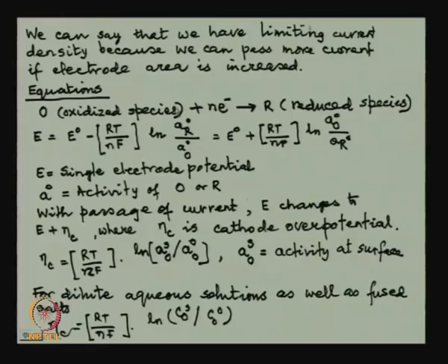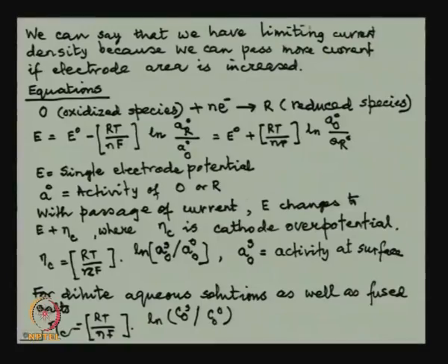Basically, an oxidized species like say metal ion is at the surface acquiring electrons to produce a reduced species. The potential for that is given by the Nernst equation. Now, you can reverse that and put it this way also, where E is the single electrode potential, A is activity of oxidized or reduced species. With passage of current, E changes to E plus eta C. This eta C is what we call the cathode over potential, because the potential depends on metal ion concentration. Now, if the metal ion concentration is dropping at the surface because of the diffusion phenomenon, then the electrode potential will change, and the change is the cathode over potential, because the process is diffusion controlled.